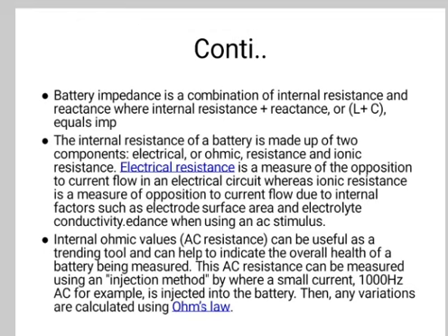In use, the voltage across the terminals of a disposable battery driving a load decreases until it drops too low to be useful. This is largely due to an increase in internal resistance rather than a drop in the voltage of the equivalent source. In rechargeable lithium polymer batteries, the internal resistance is largely independent of the state of charge but increases as the battery ages. Thus, it is a good indicator of expected life.